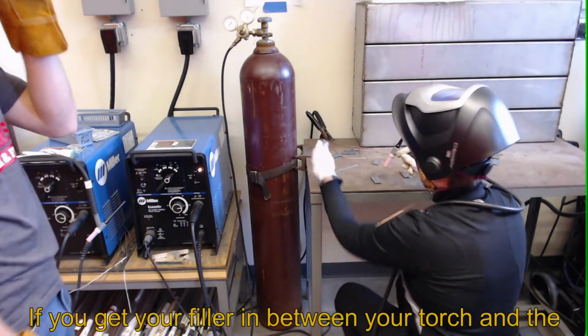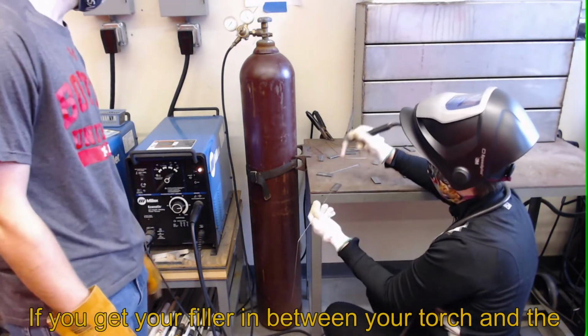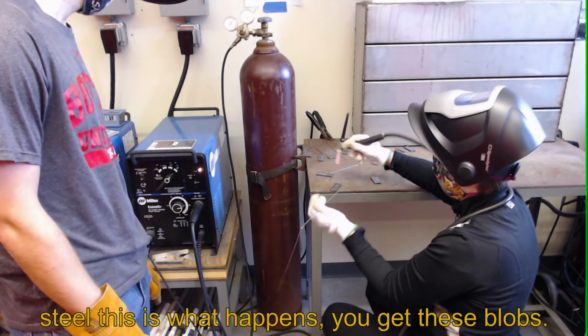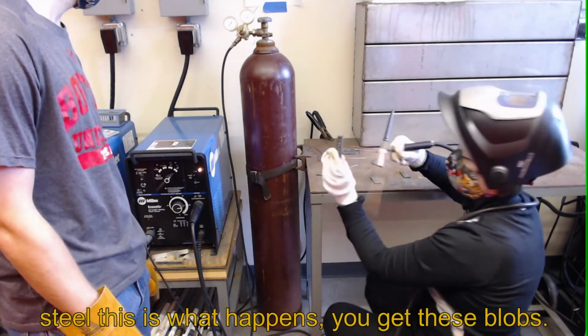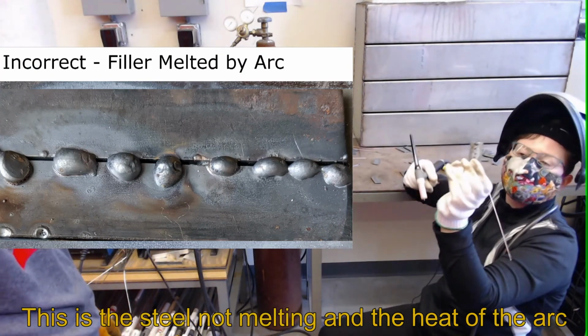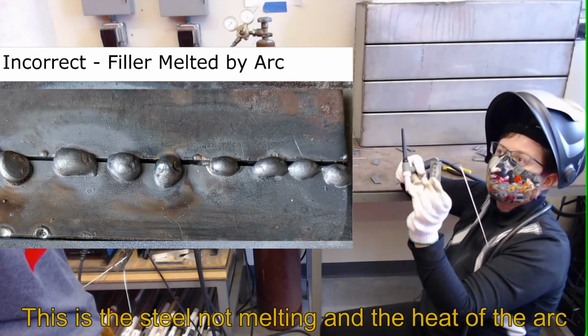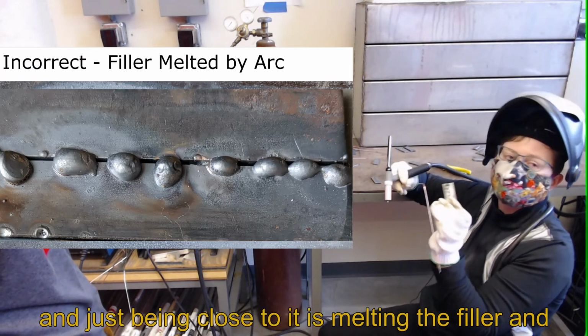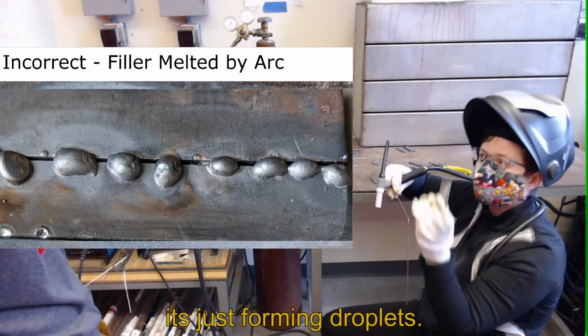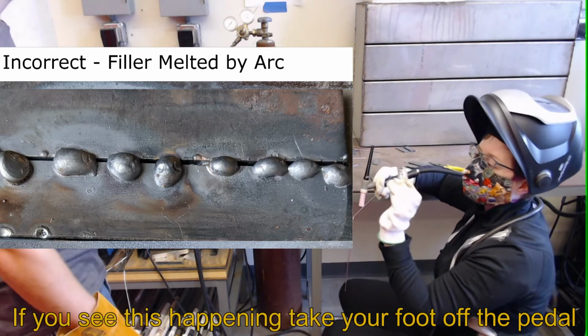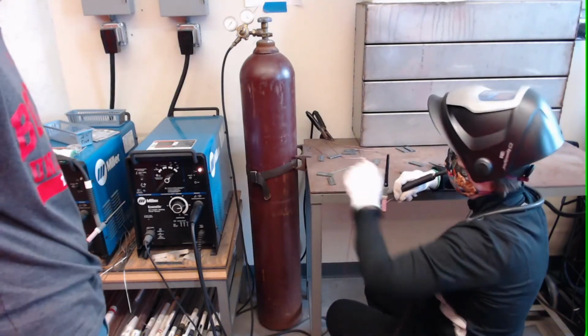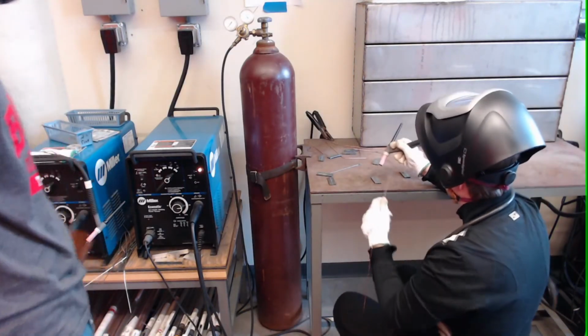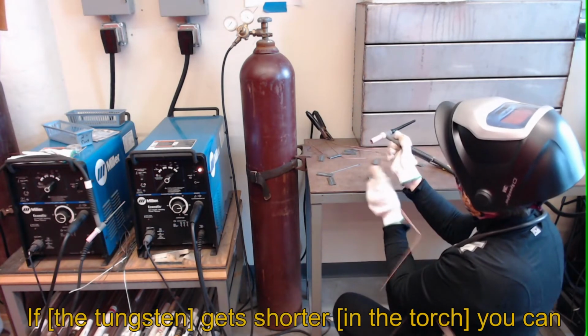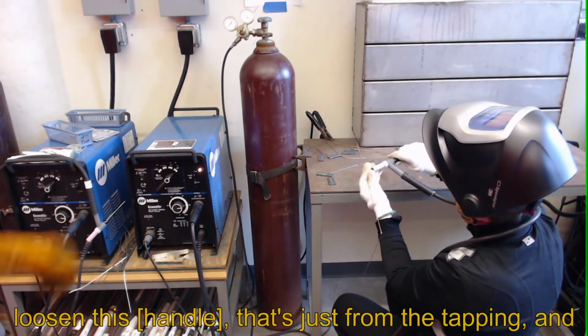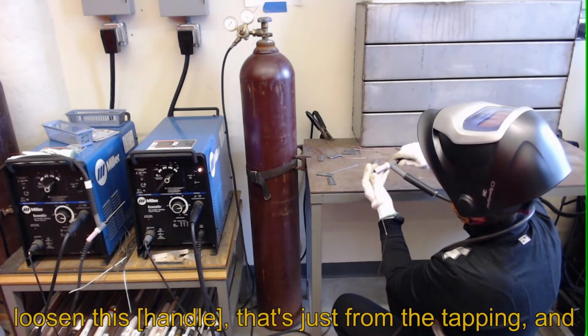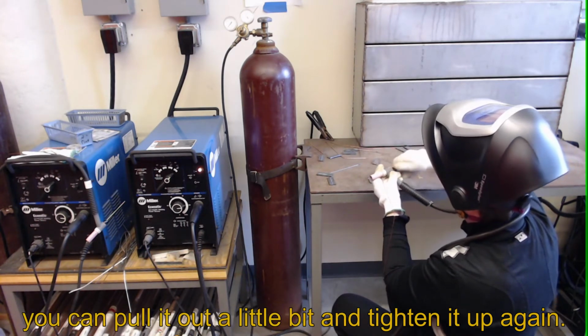So if you get your filler in between your torch and the steel, this is what happens. You get these blobs. So this is the steel not melting, and the heat of the arc and just being close to it is melting the filler, and it's just forming droplets. So if you see this happening, just take your foot off the pedal and you can start again. So if it gets shorter in here, that's fine. You can loosen this. That's just from the tapping, and you can pull it out a little bit and tighten it up again.